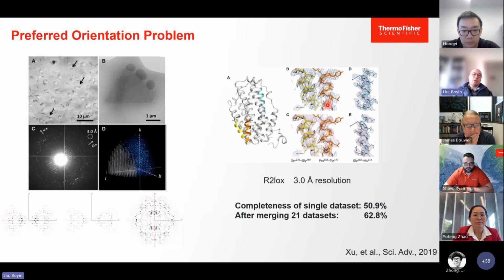Another reason we want to use cryo-FIB is that it's a potential solution for the preferred orientation problem. This example is from Hongyi's paper published in 2019. He studied a protein crystal called R2lox. This protein crystal has a very flat, plate-like shape. So after blotting, all these crystals lie down on the carbon film and maintain the same orientation. You can see their data here.